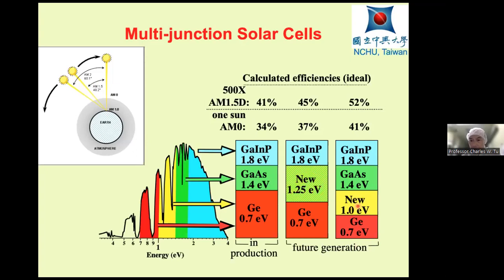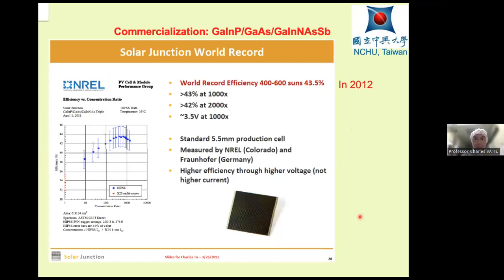a new material, 1.0 eV material, gallium arsenide 1.4 eV, and gallium indium phosphide 1.8 eV. So this 1 eV material would be gallium indium nitride arsenide, a dilute nitride, which would just fit the bill. And this was, at the time, in 2012, 2013, measured by the National Renewable Energy Laboratory, a multi-junction solar material by the company Solar Junction, and it has the highest efficiency, world record efficiency at the time. Okay.